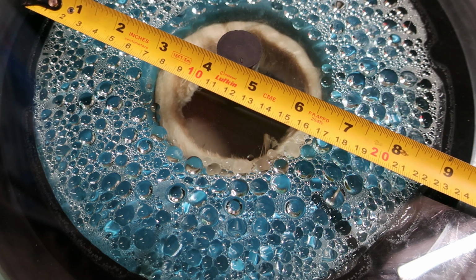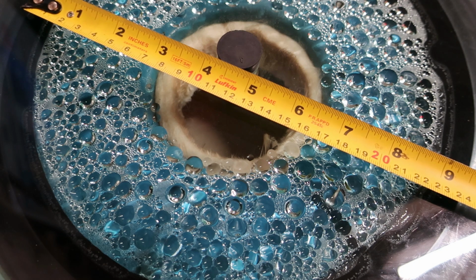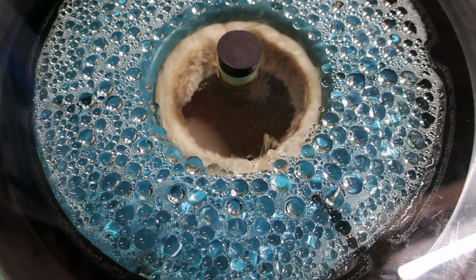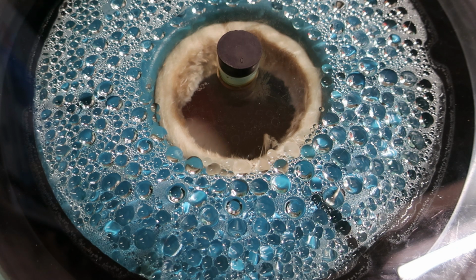And we're looking at about a 9-inch, 23 centimeter diameter piece of glass with a lot of condensation. That's a lot of water coming out of that zeolite after only an hour at temperature. And I don't think the zeolite in the middle of that can is even up to full temperature yet. And there'll also be the moisture that's condensing in the catch can.